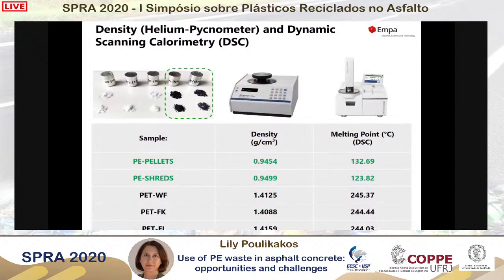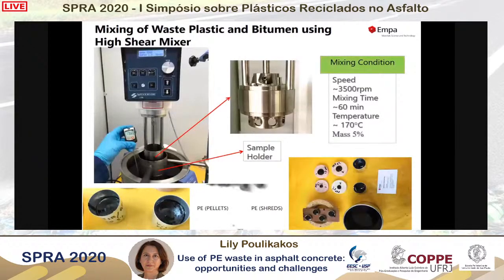Now, if we want to blend these plastics in our hot bitumen, it's important that they can melt. We see that the melting point of the two types of polyethylene is below the mixing temperature in our asphalt mixture, which is 170 in our case, whereas for the PET it is not. So we can use the PET as a sand substitute, and that we have already done in a parallel part of the project. But in this case, we are using polyethylene as an additive to the binder, and we expect it to melt within our binder. So we use a high shear mixer to add these to our binder, and on the bottom right, you see the various samples that were produced for further testing.